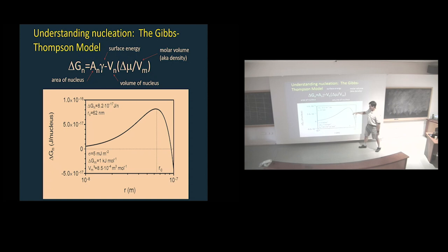And what you find is that as you have bigger and bigger ones, you're creating more and more surface area, but at one point the chemical potential term takes over, right? It's one minus the other one, and then you have this massive decrease, and now you have spontaneous nucleation of the material. Before here, the idea is that it's like, whoop, no, no, no, whoop, no, no, no. And these things are not forming a big enough nucleus to go to crystallization. So this is the story that you're told there, and this is called the critical radius, which is the minimum size you need in order for this magic to work.